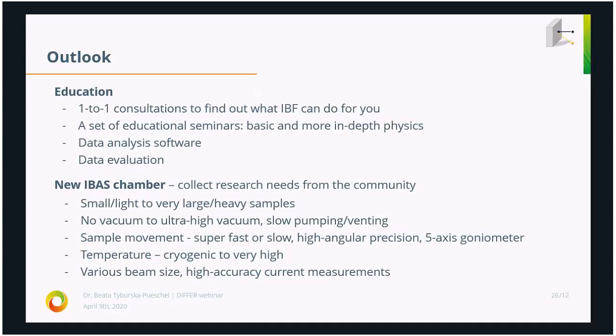Then we want to aim for a sample holder which will allow for super fast or slow movement. For example, the super fast movement could be used in those plant mutation experiments where I need 1 second of implantation per square centimeter of a sample, and then I would like to be able to quickly shift from one sample to another. We want to perform high angular precision measurements with a 5-axis goniometer for RBS channeling. Then we aim for measurements at various temperatures, from cryogenic to very high. Usually temperature has a high influence on defect mobility, so this is something I'm aiming for as well. We want to have varying beam sizes, and generally I would also like to improve the accuracy of our measurements down to 1%.